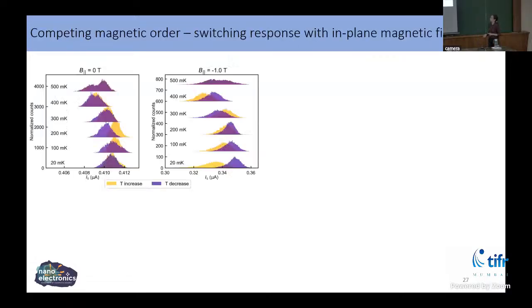So then basically what we did was look at these histograms as a function of temperature. We thermally cycled our system in the absence of an in-plane magnetic field and in the presence of one. What you notice here is that in the absence of a magnetic field, these histograms come back on top of each other, whereas in the presence of a -1 Tesla magnetic field, they don't. And in this plot, interestingly enough, the only place where these two histograms don't fall on top of each other is 200 millikelvin, which is exactly where the upturn, the direction of the beam value, changed.